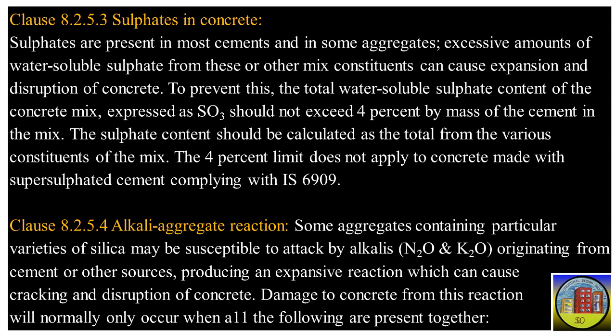Clause 8.2.5.4 Alkali Aggregate Reaction. Some aggregates containing particular varieties of silica may be susceptible to attack by alkalis, Na2O and K2O, originating from cement or other sources, producing an expansive reaction which can cause cracking and disruption of concrete. Damage to concrete from this reaction will normally only occur when all the following are present together.